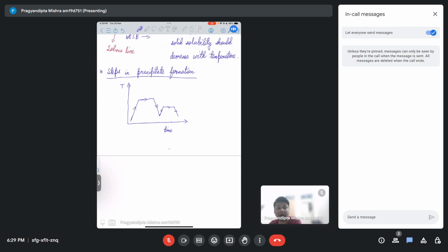It results in the precipitates starting to dissolve to an extent and start forming some phases within the material system. So this part where you are seeing this holding is known as solution treatment. You will see some temperature, let's say TL, where you're holding it. Then you will cool it down to some temperature, let's say T1. Again, you'll heat it to some temperature T2.